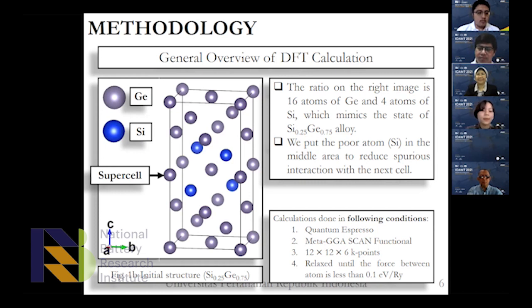supercell structure. And all calculations in this study will be carried out using the Quantum ESPRESSO package under the formalism of the meta-GGA SCAN functional. We use 12 by 12 by 6 k-points to obtain a proper electronic structure. Finally, we relax all structures until the force between atoms is less than 0.1 electron volt per angstrom.